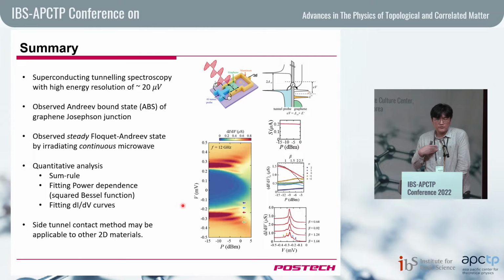Reducing the frequency requires us to have a better energy resolution spectroscopy technique. For that, we use this side tunneling superconducting contact to resolve the quantum state. And the theory, at least so far, can fit our data reasonably well. But now, we hope that after optimizing the antenna structure, and more interestingly, if we apply the microwave resonator technique that has been developed for the superconducting qubit community, we can use that kind of RF technology to apply polarized microwaves to the system and study the polarization dependence as well. Another aspect is that this tunneling technique can also be applied to other 2D materials, including topological insulators and topological superconductors, if there are any. And with that, I will conclude my talk.